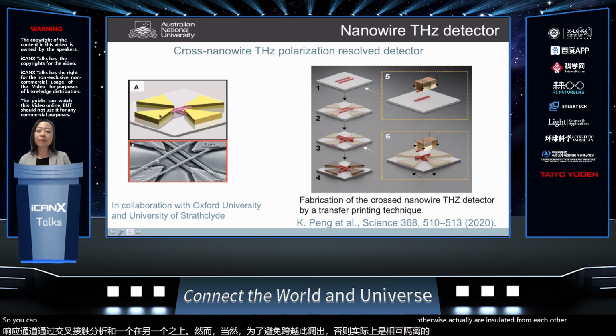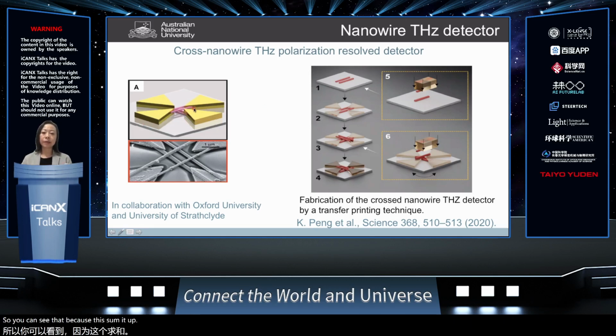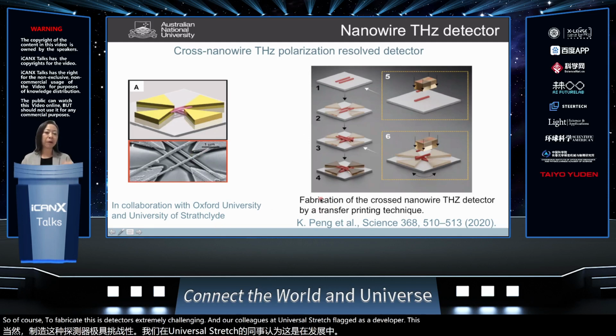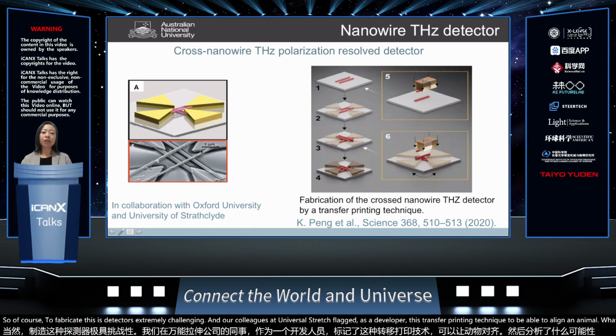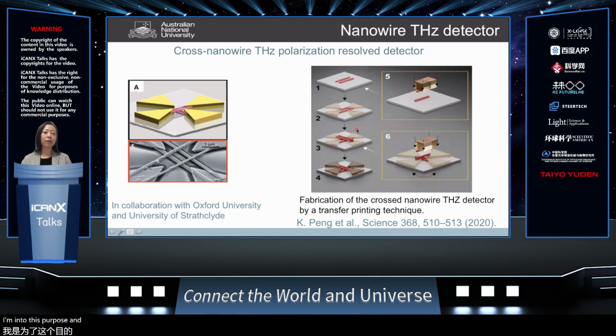So you can see that because of this perpendicular antenna shape, it actually creates a polarization sensitive detector. Of course, to fabricate these detectors is extremely challenging, and our colleagues at the University of Strathclyde have developed this transfer printing technique to be able to align the nanowire, transfer the nanowire into the proper position, and then we can make contacts on that.